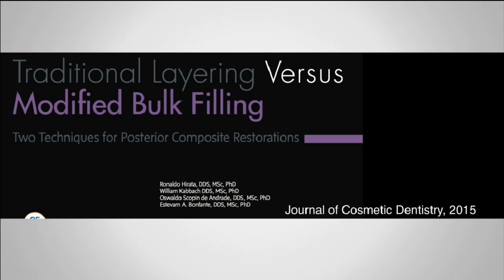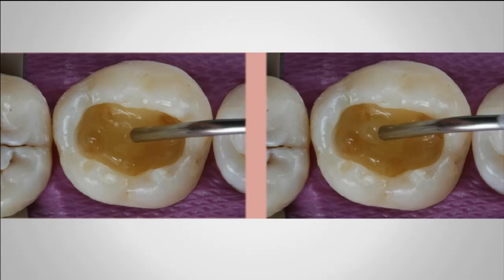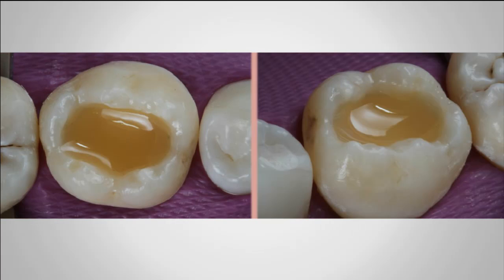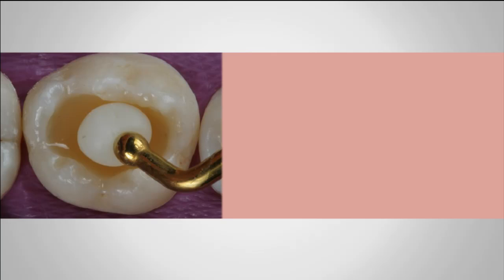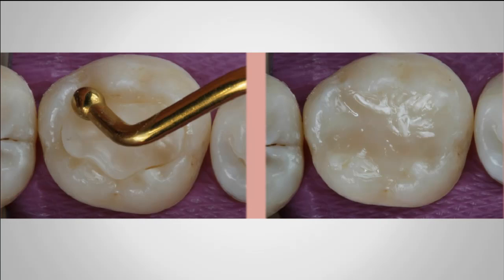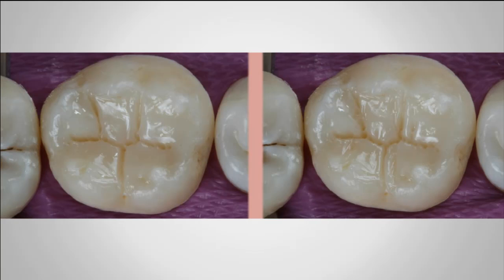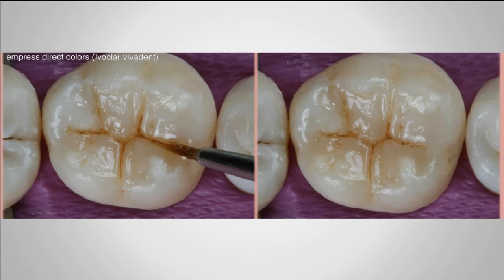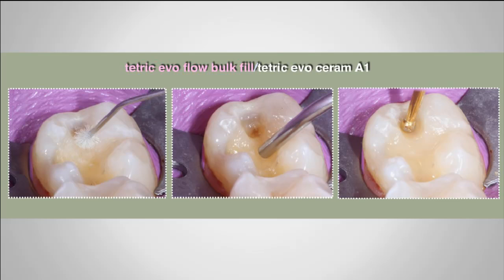And this is interesting. So we published this clinical paper, where the idea was filling a cavity up to 4 millimeters in one step. We polymerize for 20 seconds. And after that, we just apply a final layer of a regular composite. We do the sculpture. If you want to also do the staining of the sulcus, or you want to characterize the restoration, this is something that you can do as well. But you agree that these two steps are going to give us a very fast procedure and an easier step by step. So what is the idea now for us?